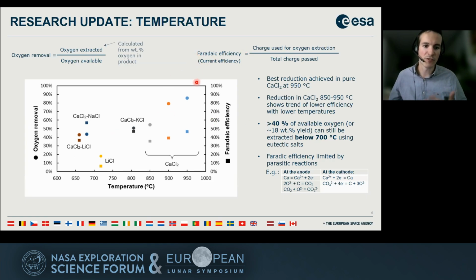Regarding the Faradaic efficiency, or current efficiency, meaning what is the proportion of electrons we use to extract oxygen, it actually drops quite a lot in pure calcium chloride. But with some salt mixtures, we reduce the parasitic reactions that can happen with dissolved calcium or with the carbon anode we use for our experiment, and we can get a better use of our electrons. In principle, we waste less current in the process. That's what you can see here. We also made an experiment with pure lithium chloride, just to show the impact of calcium chloride in the salt on the reduction process, as pure lithium chloride does not give more than 20% reduction.